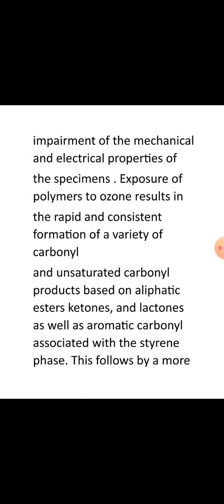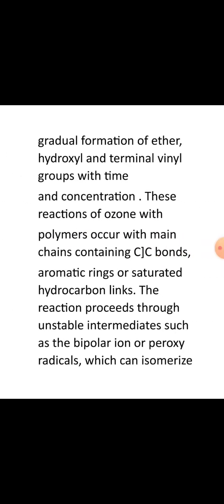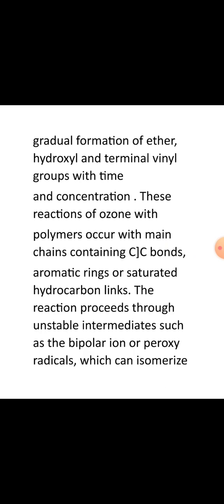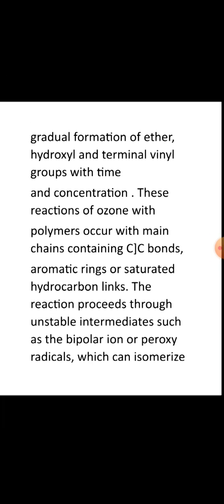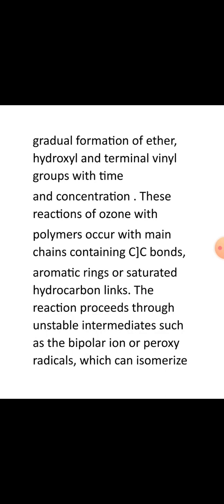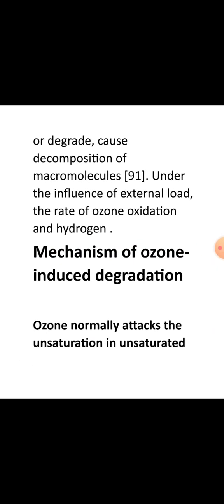Exposure of polymers to ozone results in the rapid and consistent formation of a variety of carbonyl and unsaturated carbonyl products based on aliphatic esters, ketones and lactones, as well as aromatic carbonyl associated with the styrene phase. This is followed by a more gradual formation of ether, hydroxyl and terminal vinyl groups with time and concentration. This reaction of ozone with polymer can occur with main chains containing carbon bonds, aromatic rings or saturated hydrocarbon links. The reaction proceeds through unstable intermediates such as the bipolar ion or peroxy radical, which can isomerize or degrade, causing decomposition of the macromolecule.